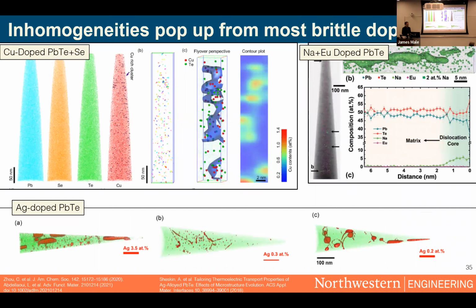And not going into any of these studies in depth, I just want to point out that this sort of atom probe tomography, identifying this aggregation or kind of clustering, it's actually been very common in thermoelectrics literature lately. People have found copper, silver, sodium, europium to all aggregate to kind of these clusters or maybe diffuse to dislocations. And in these cases, it actually improves thermoelectric properties because it's adding strain and phonon scattering centers. But simultaneously, we have to think about how it might be making our materials more brittle.